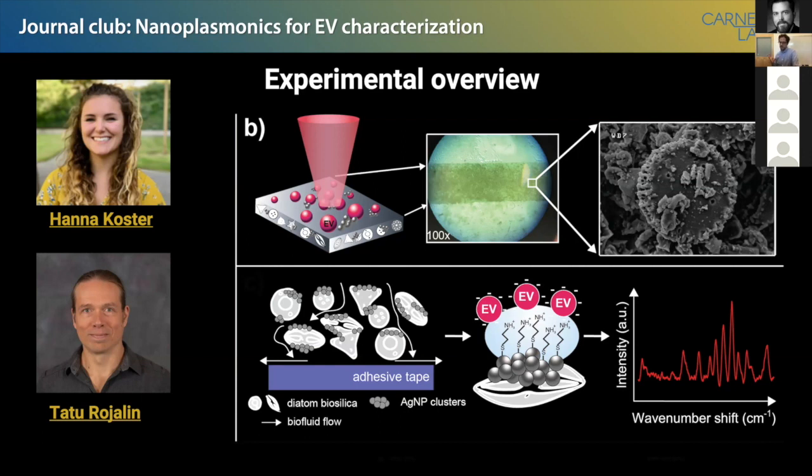So rather than using very expensive materials, you actually can just buy a bunch of silica diatoms. These are these little water creatures. You can buy them in powder from Sigma, and they're excellent photonic substrates. So we compress these diatoms. You can just think of them as a source of silica scaffold with a bunch of silver nanoparticles and literally just compress them down to form little strips, substrates.